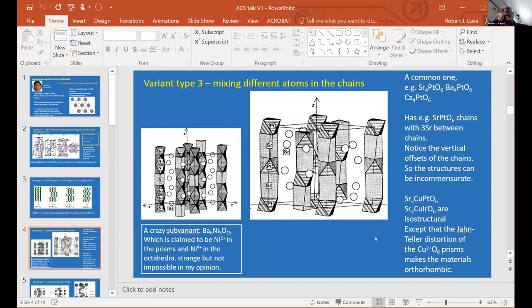And so let's say the simplest hexagonal perovskites just have chains going in one direction that are arranged in a triangular lattice. So that's the simplest hexagonal perovskite. But the chains don't need to have only one kind of atom in the chain. So in the review, we talk about taking hexagonal perovskites and taking the basic thing, which is a chain of atoms in a face sharing geometry, and then changing when they have some corner sharing allowed, and when they have other atoms that are allowed to be in the chain. Strontium platinate and calcium platinate are classical examples where you have other kinds of atoms in the chain. And if you have other kinds of atoms, you can break up this chain and break up the coupling between the metal oxygen octahedra in the chain.